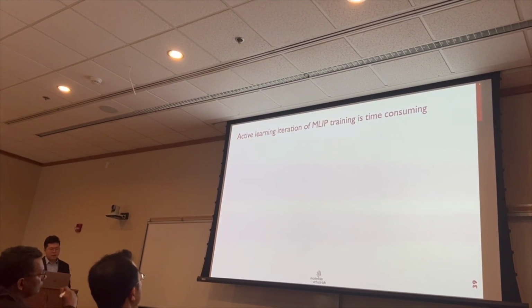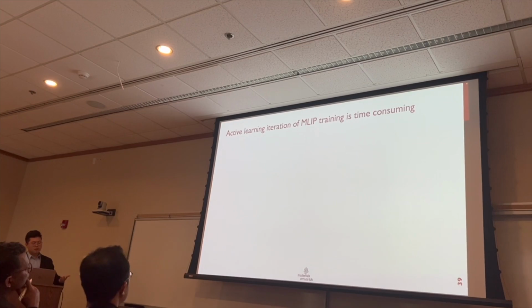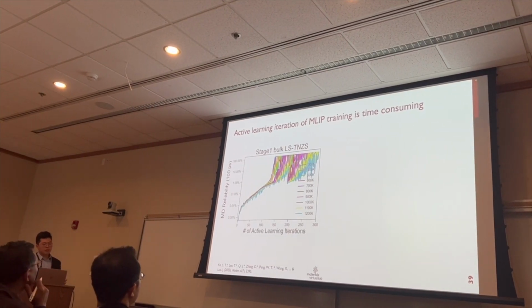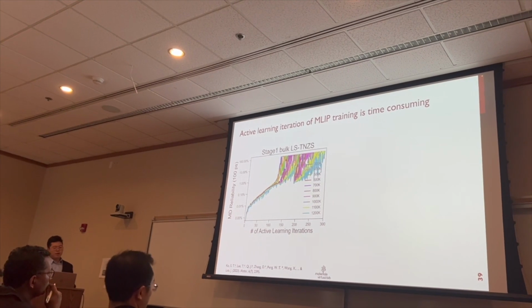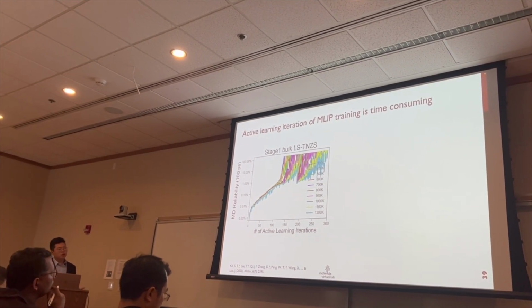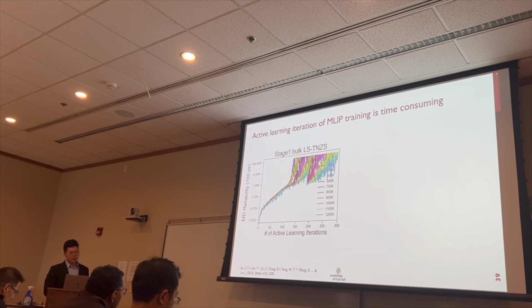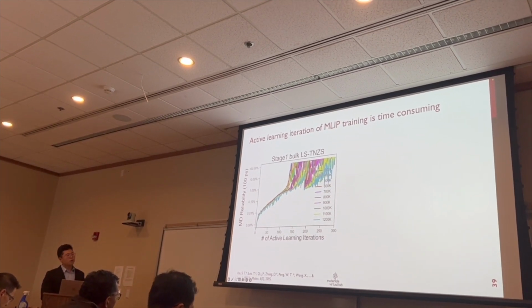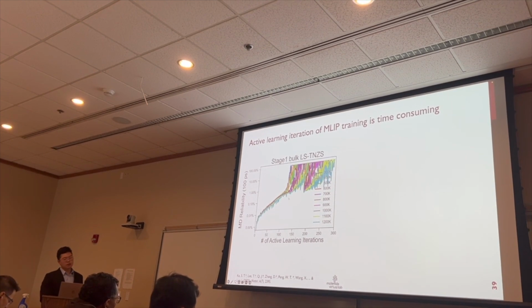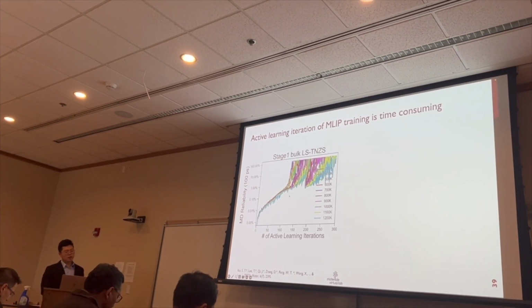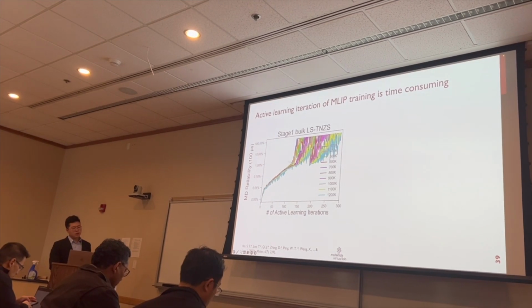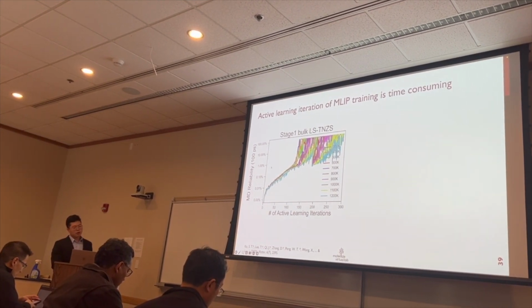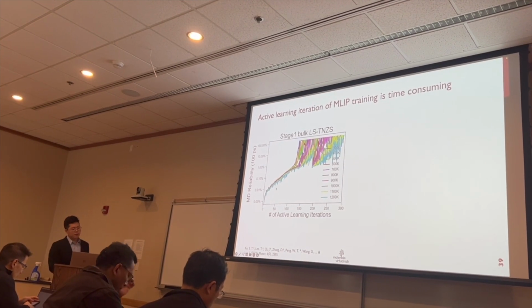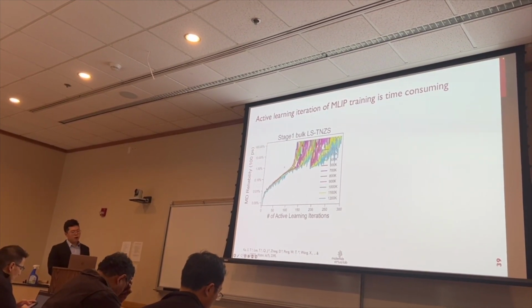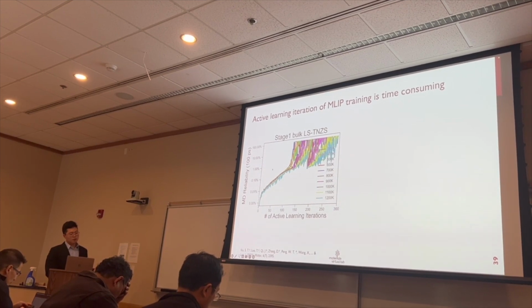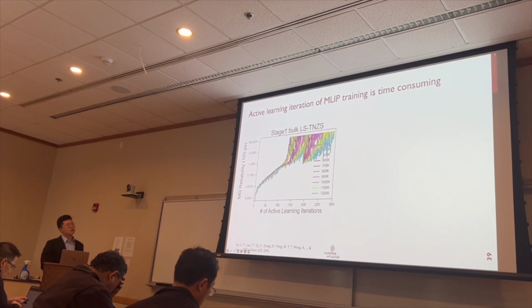So for the second part of this study, I want to first recall the result I showed previously, which is the active learning iteration that we used to fit the model for the LS-TNZS material. Here we took more than 100 active learning iterations to get the simulation converged. And especially, you can see that most of the active learning iterations are actually performed in a very small amount of MD steps, within 1% of the 100 picoseconds.